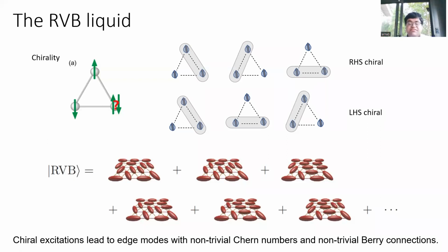You have multiple degenerate ground states, first of all, because this ground state is the same as that ground state. But what happens is that if you do an excitation, these ground states can mutually exchange between themselves because it doesn't cost any energy. And you can see that this dimer covering can go from one bond to the other, to the other, to the other without any cost of energy. And what we also find, interestingly, is that there are two different types of motion you can get. One is a right-hand chiral motion, and then you can get a left-hand chiral motion.